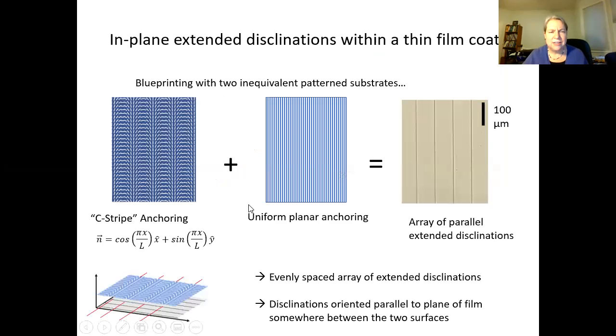Another thing we've been working on is another kind of coating where we have defects that are not little points on the surface, but are long lines of defects in the material. If we have 2 pieces of glass that are patterned, one of them has uniform planar anchoring, so the liquid crystals are lying parallel to the y-axis. Then we have another kind of structure we call C-stripes. The nematic director, as you go across the stripe, is just rotating. So theta is proportional to x. It's just going around and around and around.